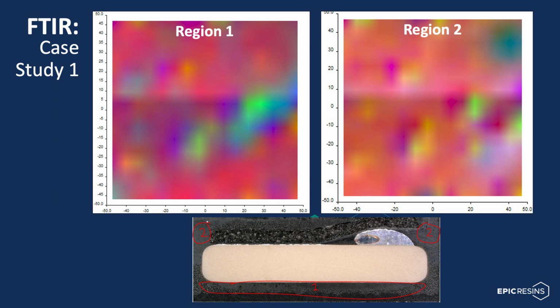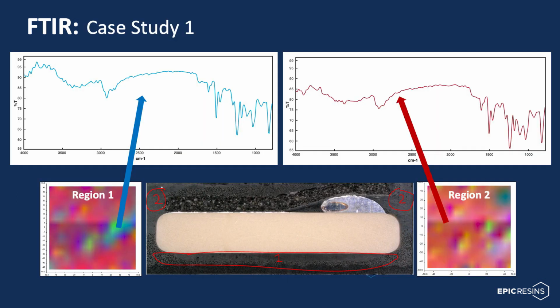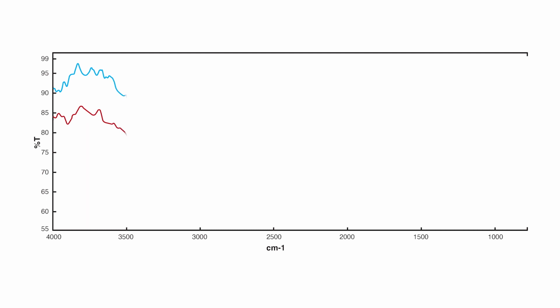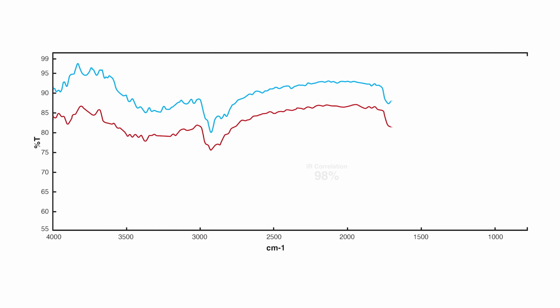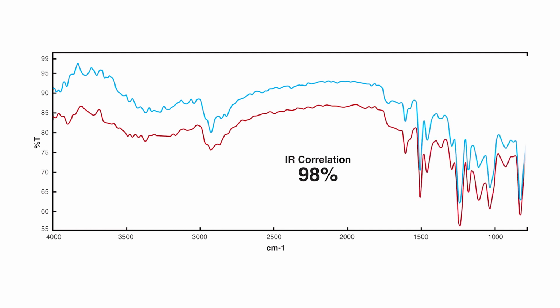These FTIR microscopic images show the array of the FTIR absorbance at these two regions. In looking at these microscopic images, we extracted the actual IR spectrum absorbance from these different regions. These are the IR absorbance spectra for regions 1 and 2. When we overlay the two IR spectra and measure the statistical correlation between the peaks, we find a 98% correlation between region 1 and region 2, indicating a high probability and minimal difference in the chemical functionality of the two regions.